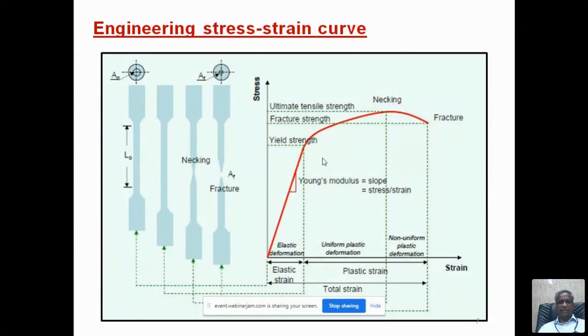Mainly, in specimen preparation, a very important thing here is the gauge length, LO, that is decided by the diameter of the specimen or the thickness of the specimen. So the gauge length LO is nothing but the initial gauge length that you have to mark after preparing the specimen. The two ends are for holding purposes. Only in the gauge length area are you going to measure all the properties of the material, so that region you have to mark specifically.